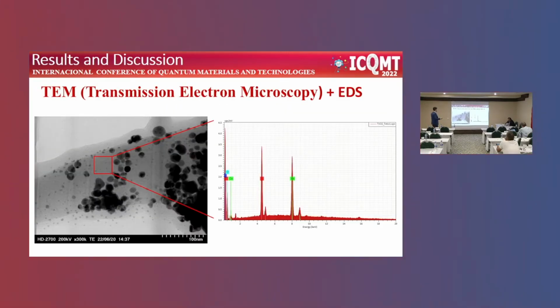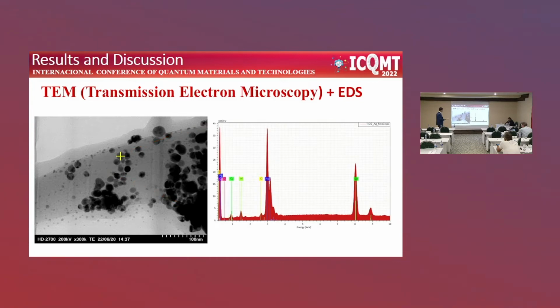Okay. When you see the transmission electron microscopy, it is in order to try to understand where the nanoparticles are in this thin film, because using the scanning electron microscopy, it's really difficult to find the nanoparticles on the film. You only can see the film and no more. Well, in the thin film, we can see perfectly that in this part the matrix is only titanium oxide, and when you put the nanoparticles over the thin film, you can show very clearly the silver. It's really clear that the nanoparticles are on the surface of the titanium oxide.